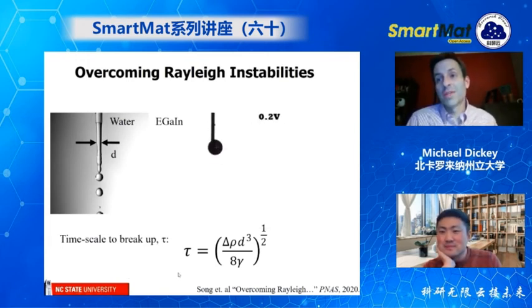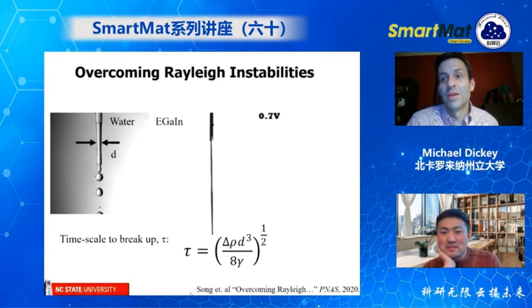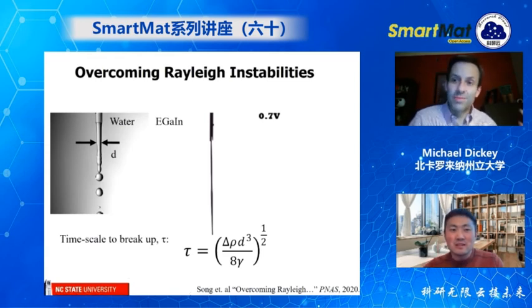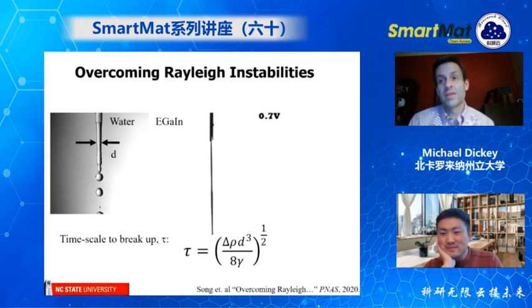What's interesting is that as the tension gets lower and lower, if you watch the voltage, it's going a little higher and higher. At some point, the surface tension basically goes to zero, and it comes out as a perfect cylinder. So I'm answering your question in a roundabout way, but yes, the size does matter because it affects the gravitational forces. I don't know how small a structure you can do this on, but you can see here we've done it down to 100 microns or so, and it works.